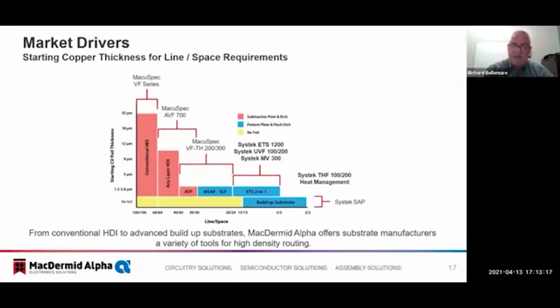The vertical axis shows how the starting copper foil thickness has decreased over time to more carefully control the copper budget, to minimize the amount of copper that's ultimately needed to be etched. The rectangles illustrate how the evolution of fabrication techniques to attain finer lines and spaces have progressed through conventional HDI type fabrication techniques through any layer to MSAP, and finally to the embedded trace and 2-in-1 RDL plating. And then finally, along the tops of those rectangles, you can see how our product offerings have progressed to enable these different types of manufacturing techniques.